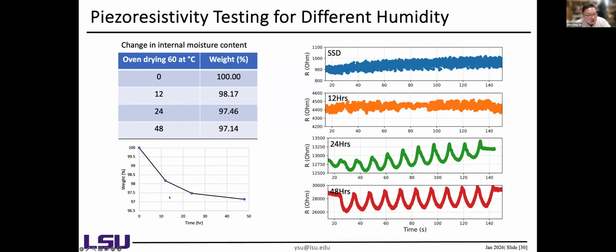As you can see, it's time versus the weight. So we put it into the oven at 60 degrees Celsius for 12 hours, 24 hours, until 48 hours. As you can see for the SSD, if it is fully submerged and the humidity is 100%, then you get a lot of noise, which is really hard to interpret. And if you only dry for 12 hours, still the signal is not obvious. But if you dry further to 24 hours, we can start to see the trend of the cyclic loading. And for 48 hours, we got a better signal.